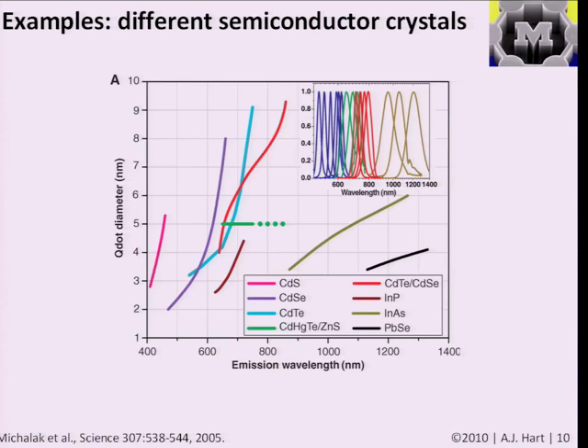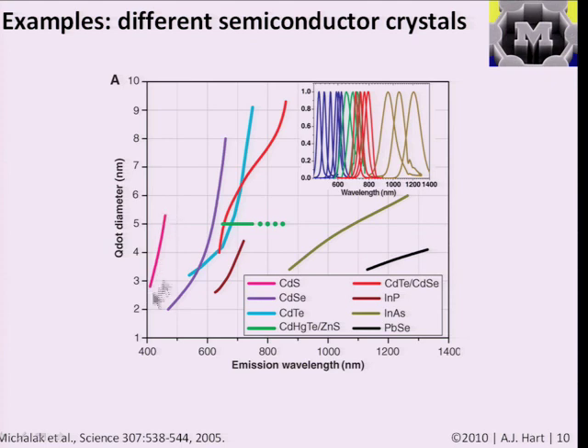Because of the utility of these materials for imaging, you can put chemistry on the surface and hook them to other molecules. Using different materials in different sizes, you can get emission wavelengths over a broad range—from the narrow visible wavelength all the way up into the infrared. There are certain trends with size, and because of the intrinsic properties of the material itself, cadmium sulfide covers a narrow 400 to 450 nanometer range from three to five nanometers. There are also core-shell structures, where one material is in the center and another on the outside, to manipulate the effect of surface states. Oxidation of the surface of a particle can affect optical properties because the excited state gets trapped at the surface and may decay non-radiatively, transferring heat to the lattice rather than emitting light.